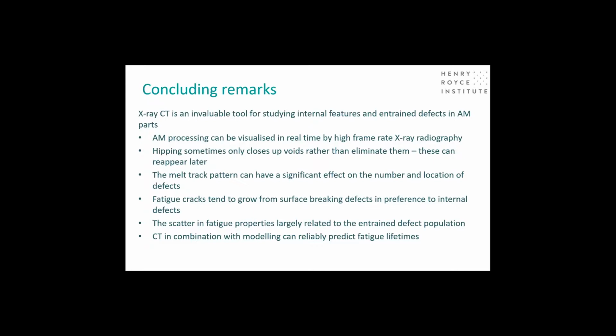One other point I would say is that traditionally, the kind of imaging that I've shown might take minutes or hours to undertake, but there are other ways of scanning in CT where you can combine that with production line type frequencies. So we've been working with a company who scan baggage, and you can imagine baggage scanners, they can scan thousands of bags per hour. And we've been working with them to develop CT systems that will scan thousands of parts per hour. So in that case, you can scan both the external structure and the internal microstructure at a rate of about one article per second.